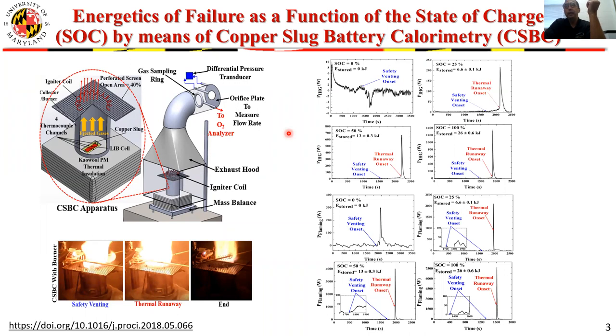So we designed our own method that we called copper slug battery calorimetry, that evolved through a number of iterations, and more or less the final iteration is shown here on the slide. The idea of the method is pretty simple. Again, the goal is to measure heat that is produced by a given single lithium-ion battery cell upon failure. That goal is achieved by taking a cell and charging it to a given state of charge. State of charge is the fractional charge with respect to the nominal capacity of the cell, with 0% indicating that the cell is completely discharged and 100% indicating that the cell is fully charged.